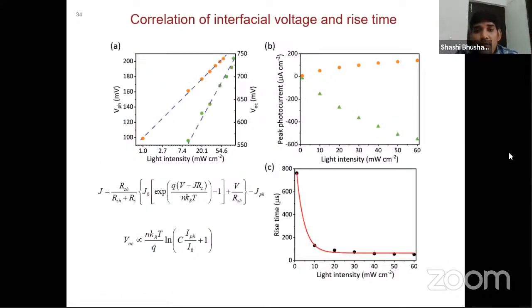Further, we used the electrochemical measurement and tried to see the light intensity control over peak photocurrent. You can see that it is more or less, you cannot say linear, but it has a slow decay in the exponential mode. With this relation, you can understand that this is the JPH and this is the exponential of V minus JRS. So this relation clearly shows this kind of behavior.